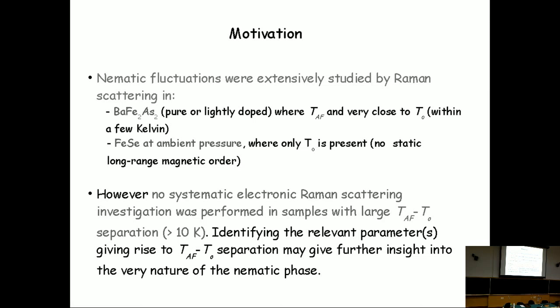So we note that there is no systematic electronic Raman scattering investigation for materials where we have both the magnetic and the structural transition temperatures well separated by more than a few degrees. And we think that's an important case, because in this case there is potentially more disorder, and this disorder can actually give us insight on what's going on here, up to a point, of course.